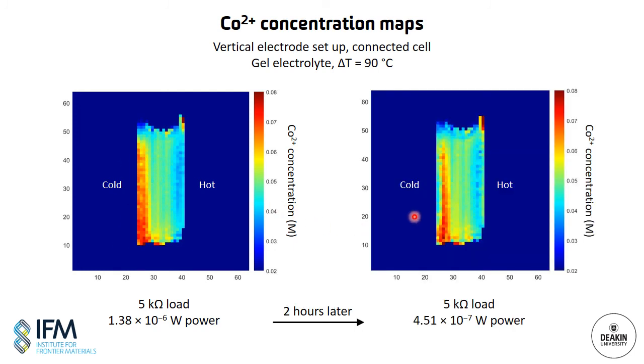After 2 more hours, we do start to see a layer of cobalt 3+ being formed on the cold electrode, as expected, and what looks like some increase in 2+ concentration on the opposite side. So clearly we need to run some time resolved tests on the unconnected and connected cells to differentiate these two processes, but we haven't done this yet on the vertical electrode setup.